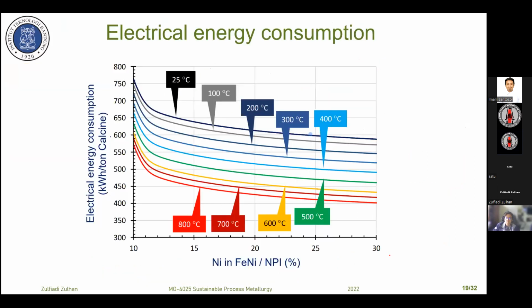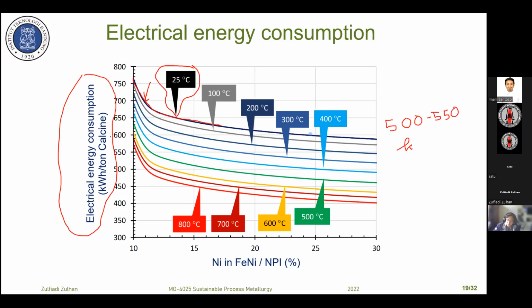This data shows you the typical electrical energy consumption. It depends on the temperature of the calcine which we charge into the furnace. If we charge at room temperature, as in this typical calculation, the energy consumption is very, very high. The common energy consumption right now for the furnace is around 500 to 550 kilowatt hour per ton of calcine, the common electrical energy consumption.